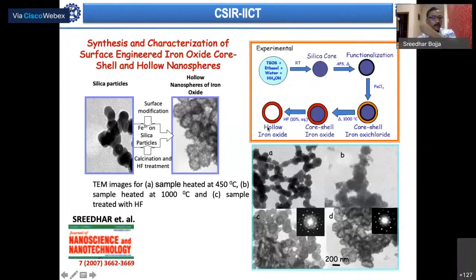Then we tried to look at synthesis of hollow particles of iron oxide, because iron oxide is a very interesting material for drug delivery and other applications. We wanted to make hollow particles of this and work on it. The precursors are the same: you have the silica core, functionalize it, then use iron chloride as the precursor for iron oxide, giving core-shell particles of iron oxychloride.